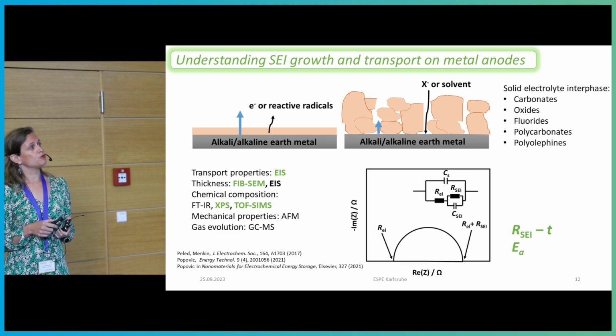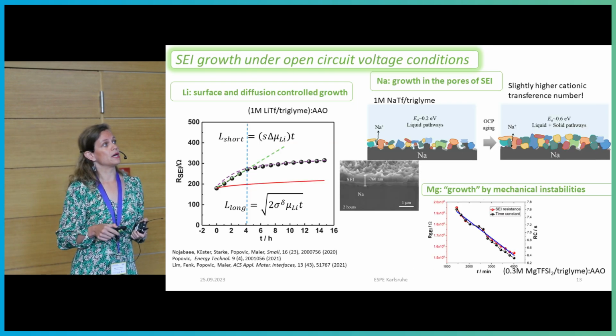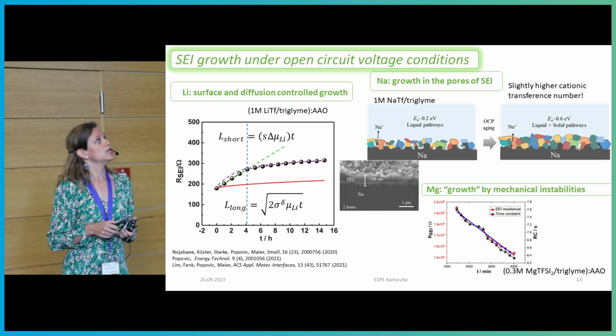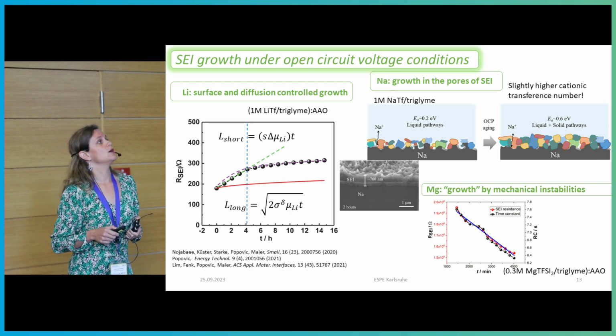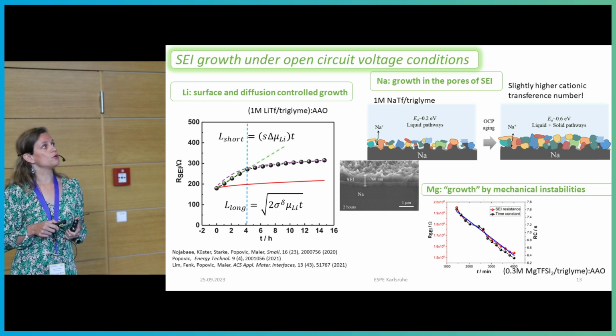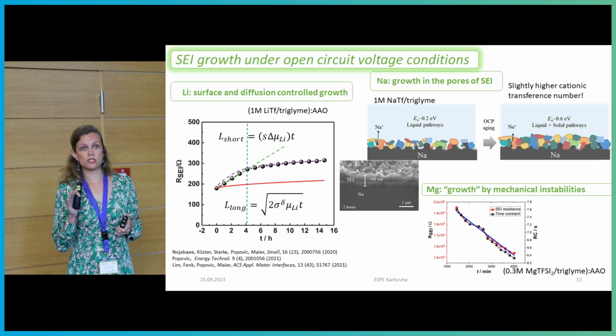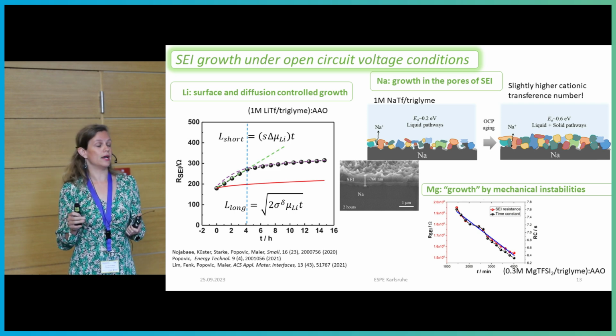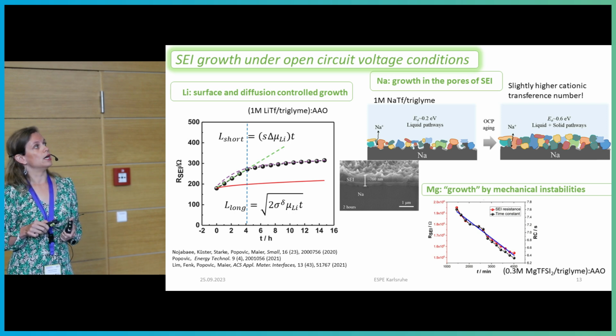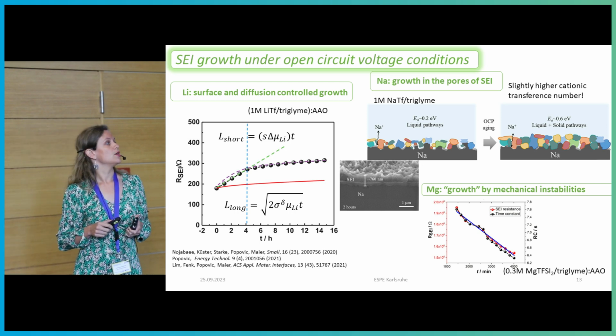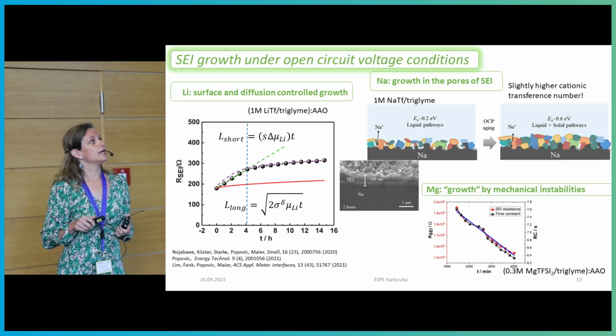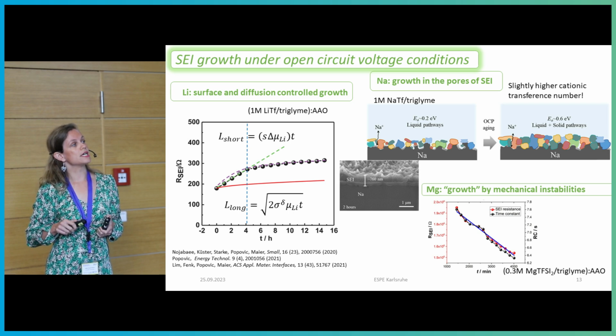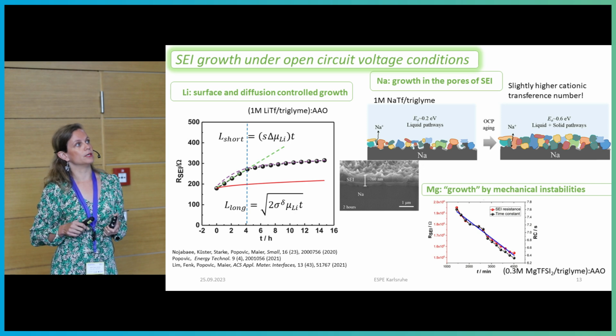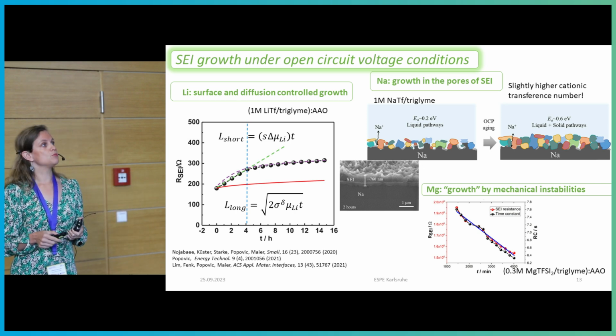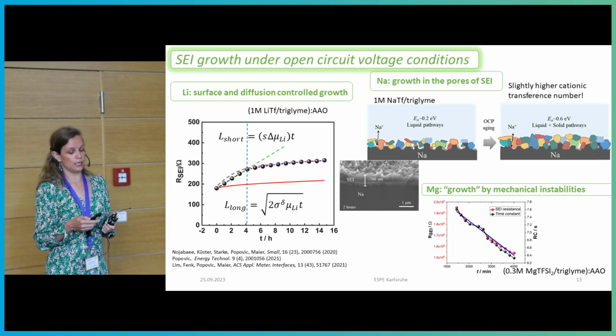So here are examples of what we have found in terms of lithium, sodium, and magnesium in some specific materials. If we look at lithium in the glyme case, we could see a change in the growth mechanism. I'm talking only about open circuit voltage conditions. This is really important. That means no current has been applied in these systems. We see a change from surface growth to diffusion-type growth. That is something that we know from SEI growth studies on carbon. And in the case of sodium, we see that a very porous SEI grows at the very beginning, and the pores get filled in with time. And in the magnesium case, we see quite a lot of mechanical instabilities in long-term growth.